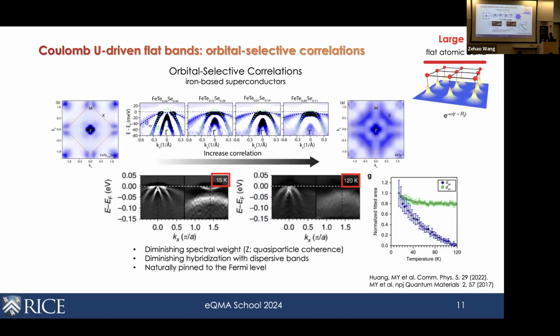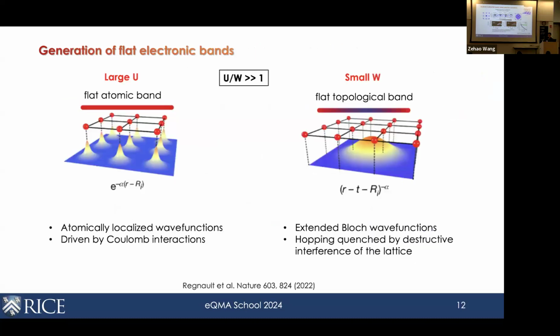Okay, and then in addition, what we can also see is that as we traverse this tuning axis, or also in the temperature regime, we can see the spectral weight for this band disappears eventually. And that's shown here experimentally by these fitted points, which are the areas under the XY band as a function of temperature. Okay, so that is what we already know, and also similar to the cuprates and other systems for the regime where the flattening of the band is driven by correlation, by Coulomb interactions.